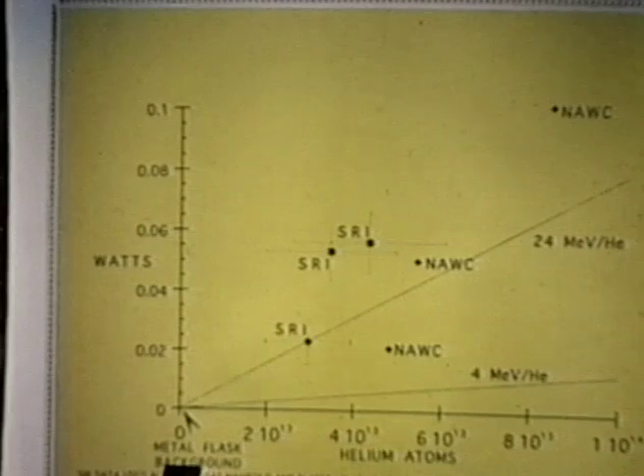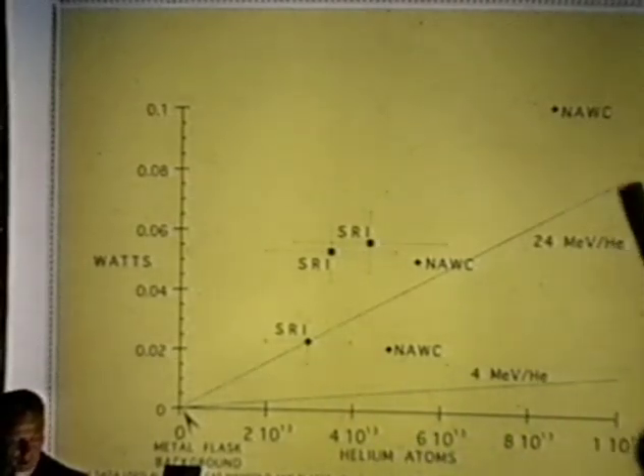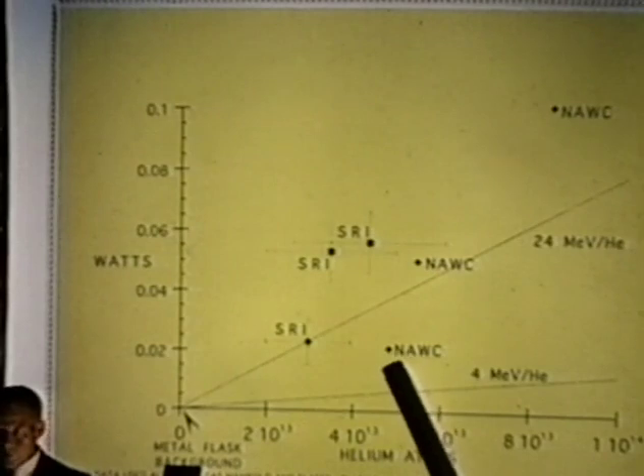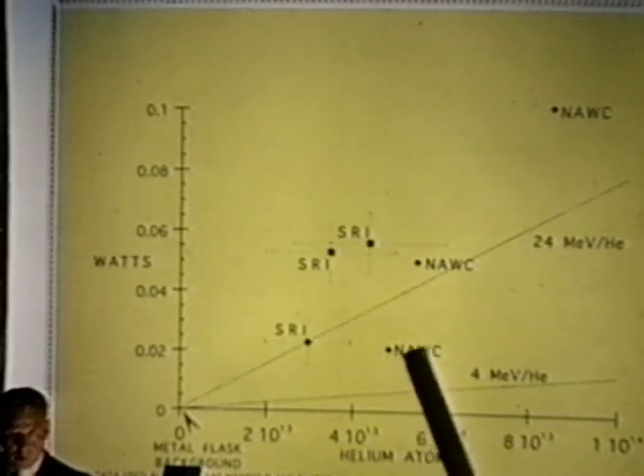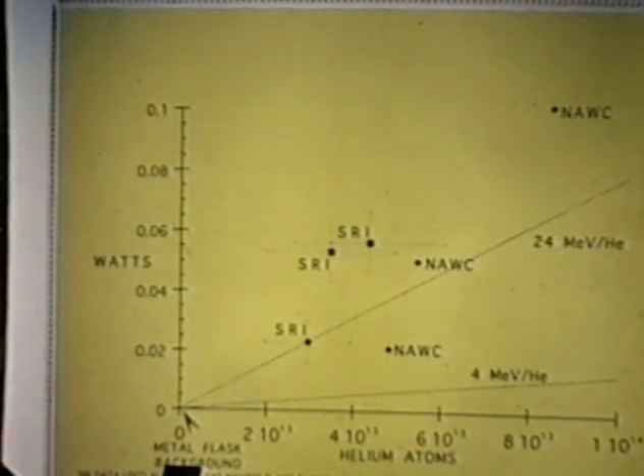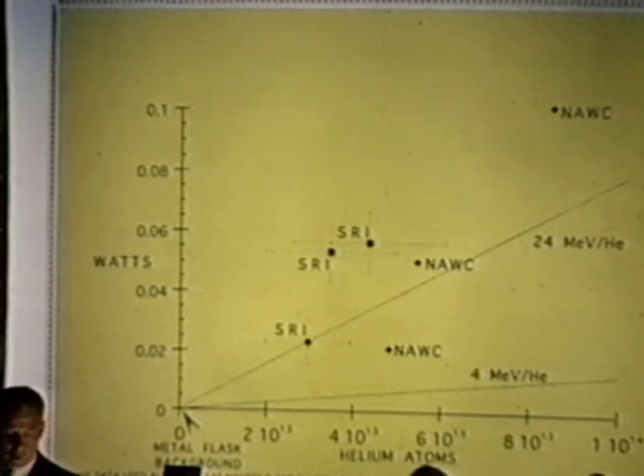But if you plot our NAWC, our name is now Naval Air Warfare Center, so we're now NAWC, but if you plot this versus energy, you have the 4 MeV line and 24 MeV line. You see that we do have some results that come close to explaining the helium that we see. And this is some SRI results measured by Ben Bush, but we are at least in the neighborhood or order of magnitude of what you would expect based on a fusion type reaction.